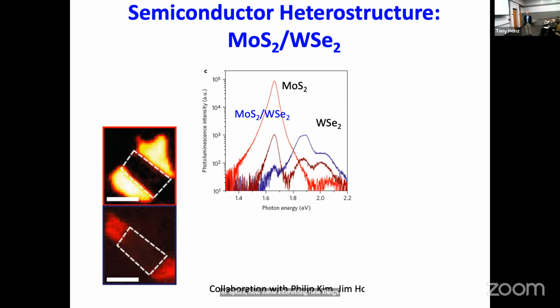So just to show you in the context of optics how some interesting new things emerge, we took two of our favorite semiconductors, put one on top of the other. And then this is looking at the optical emission spectrum and the structure of one thing going this way, one thing going that way. If you look at the respective emission for this material at the right wavelength, you see plenty of emission here and here. You look at the emission for the other material here and here, you're in good shape. But what about this box? The box is where they overlap. You see hardly any emission. This is a log plot of the emission. And you actually see sort of similar features, but very, very strongly suppressed.